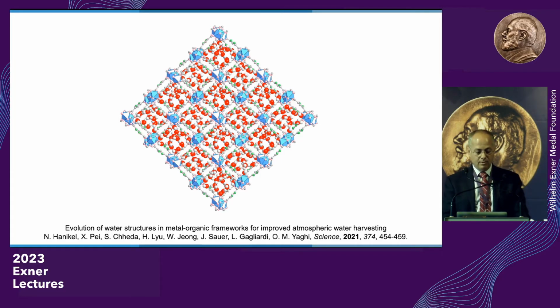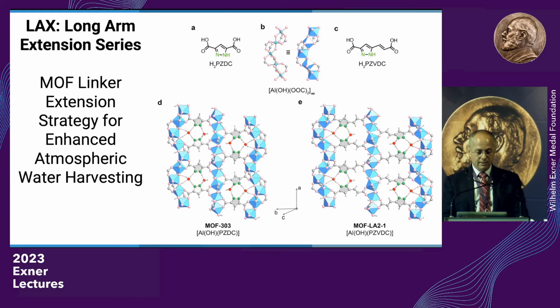And so our idea was, this is MOF 303 and this is a linker. We tried many things, like adding another 5-membered ring to the linker to make it longer. Well, that produces a MOF that is not so stable in water. And then we used 6-membered rings. Then the 6-membered rings are too large. They wedged themselves into the pores and used up the pore volume. And so you didn't get much for that.